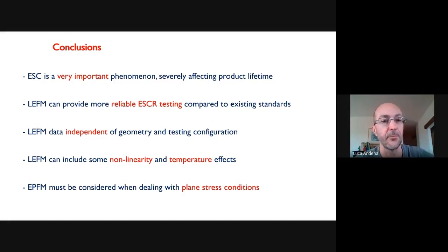So you can immerse the material, for example, in a given medium for 2 years, but if the medium goes away before you apply some mechanical load, nothing bad happens to the material. However, if you have the simultaneous presence, then you have to be very careful. There are some standards to characterize the resistance to this phenomenon. However, they're a bit lacking in terms of accuracy and sensitivity. And also they cannot be used to make predictions. So you can tell, okay, material A is probably better than material B, but I have no clue as to how long a product may last in those conditions.